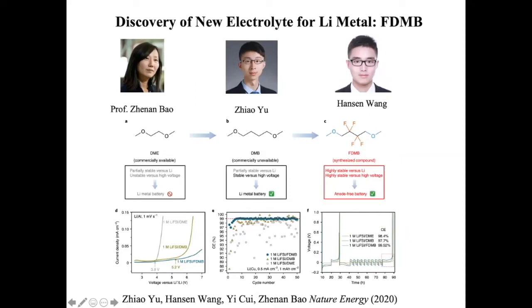This is the first time making this molecule. It has an amazing effect as a solvent. With these three different types of molecule as solvent, we compare, right? And this FDMB, with fluorine, can stabilize and go up to higher voltage during the current versus voltage measurement. And in this half cell, the lithium copper half cell, the cycling Coulombic efficiency goes up to quite high within 5 cycles. You deposit, you strip, and right away it is more than 99%.